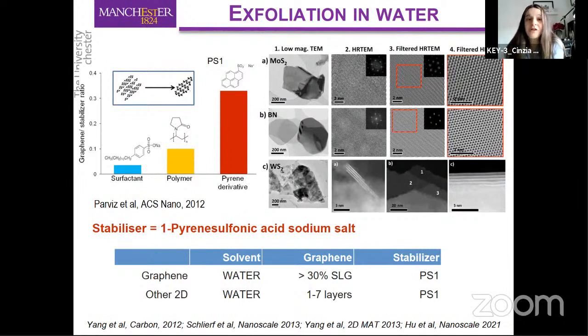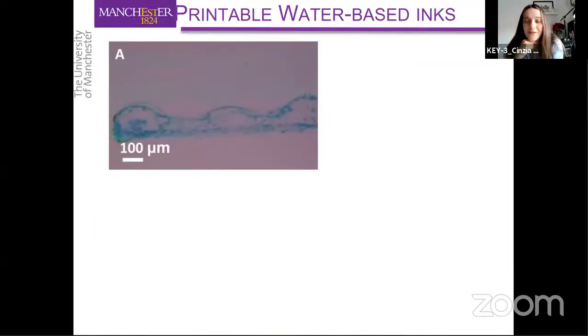However, as I mentioned to you, water is not a good solvent for inkjet printing. So if you try to print those formulations as they are after exfoliation, then you will not get very good results. This is indeed the picture showing the printed graphene, the very first attempt that we made by printing those formulations without any modification. And you can clearly see that there is a very strong coffee ring effect. The material is completely randomly distributed. The concentration is actually even too low, and the line will not even be conductive. So that means that we still have to perform some modification that can be done post-exfoliation.